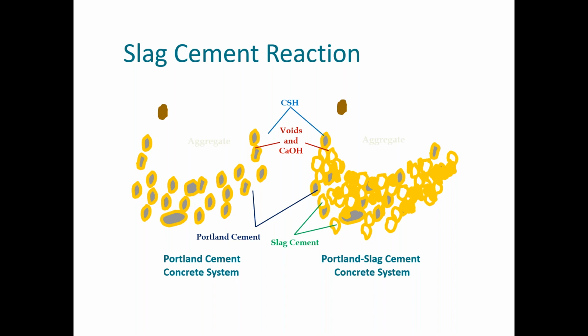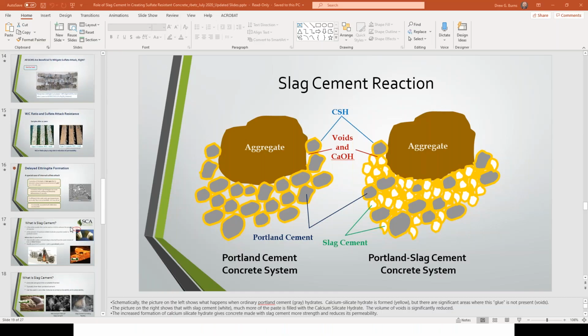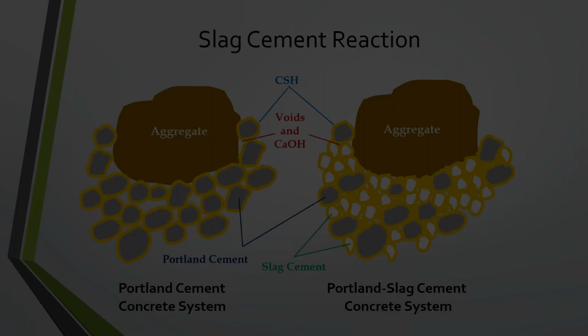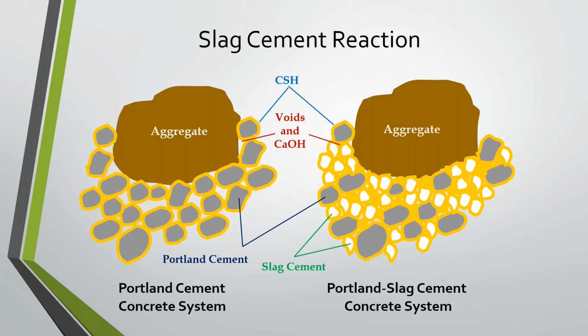This isn't as dramatic as it seems, but when you look at the difference between the slag cement matrix system and the Portland cement system, you notice that there are far fewer voids. There we go, perfect. So this is a little better representation. Now you can see what I'm talking about. This is an overdramatized version and not accurate to scale, but the idea is that the free lime, the lime not used in the cement hydration process, is actually beneficiated by slag cement, and it helps create some additional hydration product. So what you end up with is a less porous pore structure of your paste.